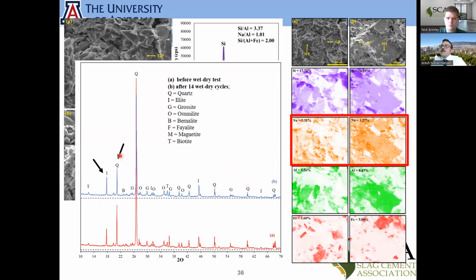And if we check the XRD patterns of the samples, we see that the crystallinity of the material is there. And obviously, the geopolymerization is good. For the geopolymerization, we could look at the area below the patterns, the area between these dashed lines and the XRD patterns. So the geopolymerization is strong.